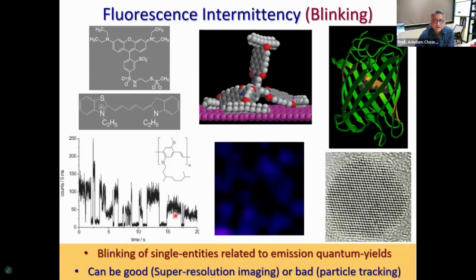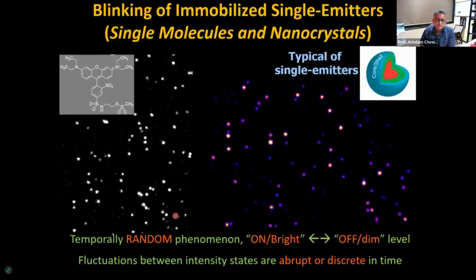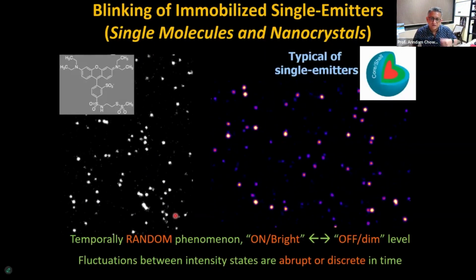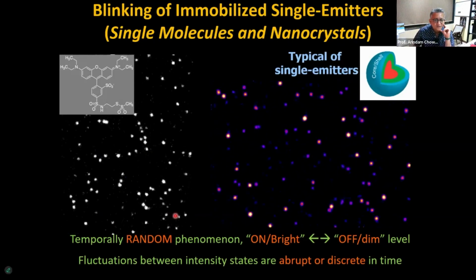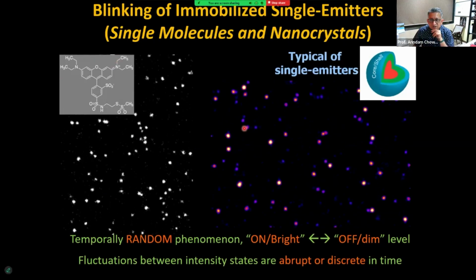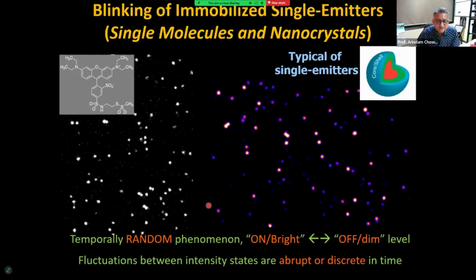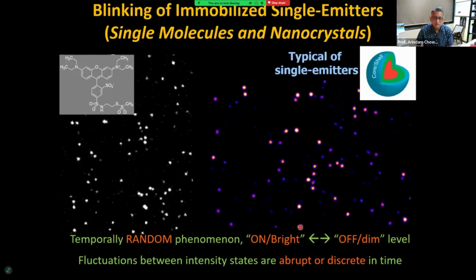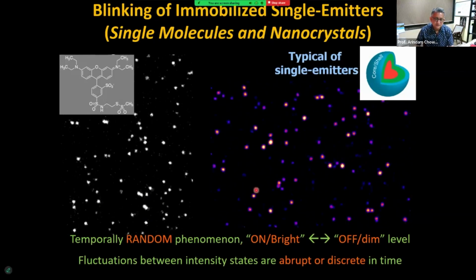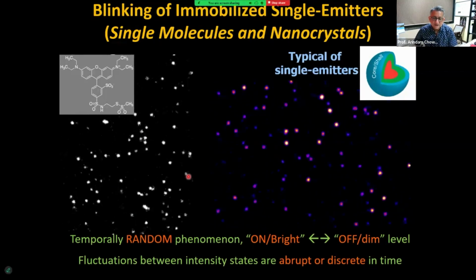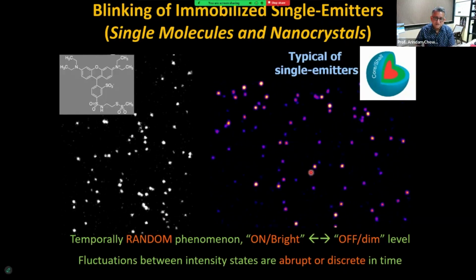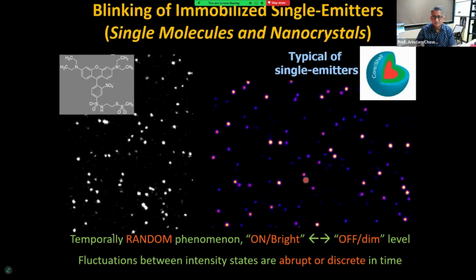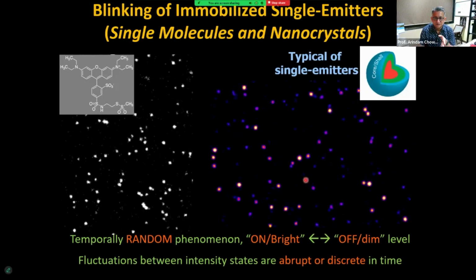If you want to track a molecule, then if it turns itself off, the light doesn't come out, then you can't track it. Now, if you take a bunch of fluorescent molecules under ultra dilute conditions, for instance, rhodamine 6G here on the left, or some nanocrystals here on the right, and you put them on a glass cover slip and collect a movie, and then you start seeing these kind of spots. You can see it's a temporally random phenomena going from an on to an off state for semiconductor nanocrystals as well as molecules. And these fluctuations that you see are abrupt or discrete in time. That means they're very sudden in time. They're not gradual in time, all right?